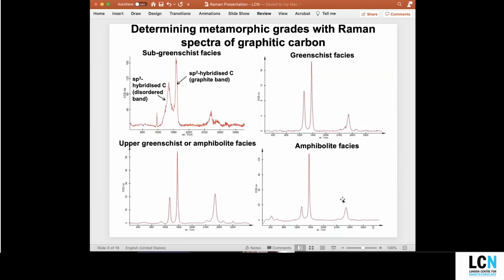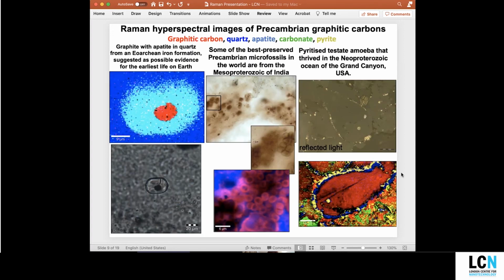The bottom right is better shown in this other figure, which shows the D band, the disorder band of carbon, the sp3 hybridized carbon, versus the sp2 hybridized carbon of graphite, and that changes with increasing levels of maturity and crystallinity, and therefore can be used as a thermometer, a geothermometer in our case, but a thermometer in general.